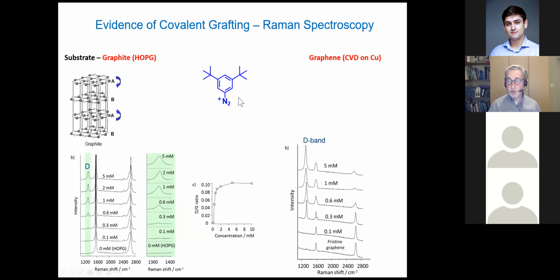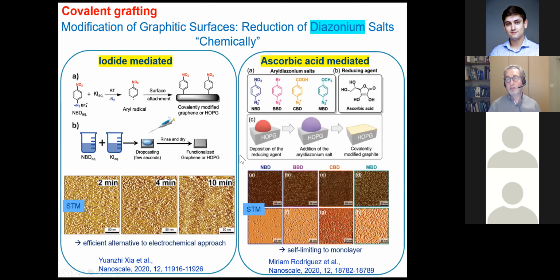Of course, there is still the question, do you really have a covalent attachment on the substrate? And we believe we have, because Raman spectroscopy is a very sensitive technique to establish any type of defect introduction in graphite as well as in graphene. And particularly the D band here is typically accepted as a good marker of the formation of a covalent bond. By doing these Raman experiments, we could indeed establish that as a function of concentration, we have more and more of these covalently grafted molecules.